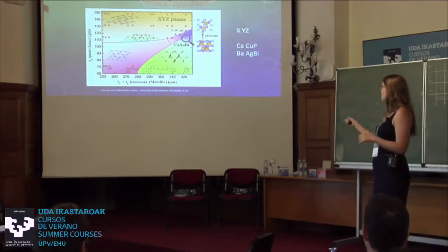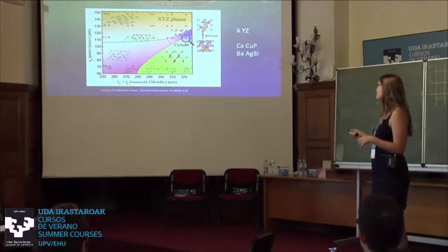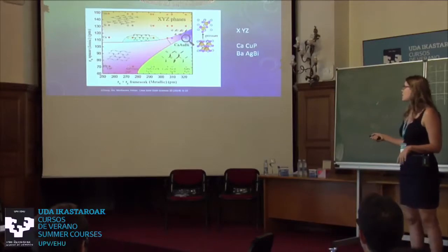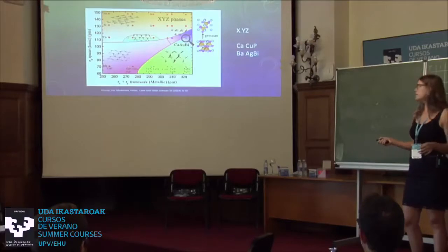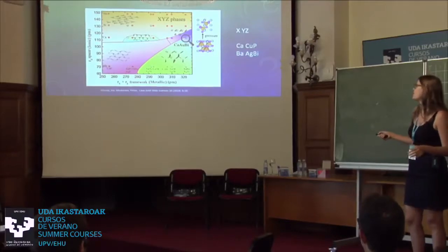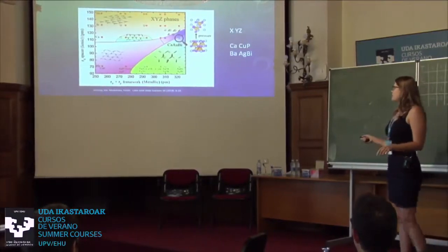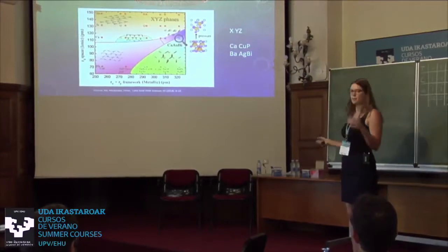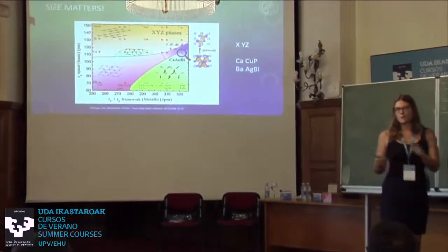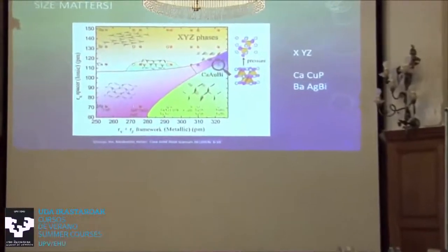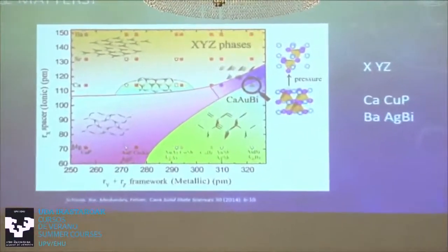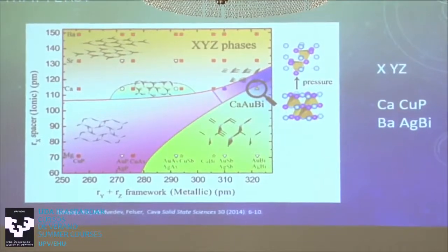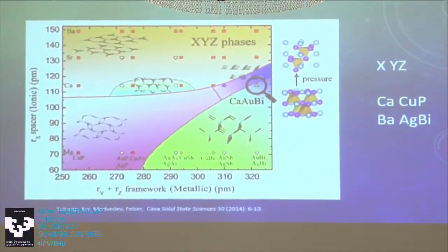So this is a typical structural map you can have in solid-state chemistry, where you plot the radii, so the size of the atoms in your crystal structure on one axis, and also the size of other atoms on the other axis. So this is a map for X, Y, Z phases, so 1 to 1 to 1 phases again. All of them have 18 electrons, so all of them are charge balanced. And we put the radii of the X atom here. So the X atom is barium, strontium, calcium, or magnesium, some kind of rare earth. And then we put the size of the other 2 here, like the sum of the sizes.